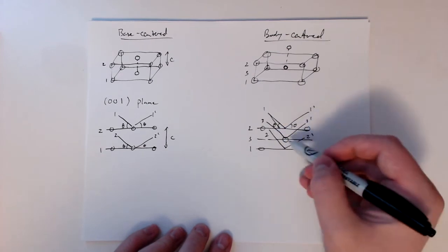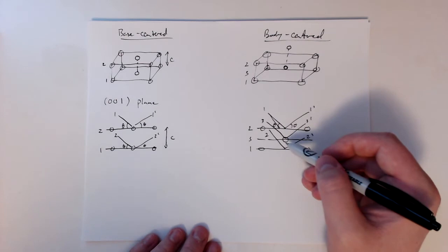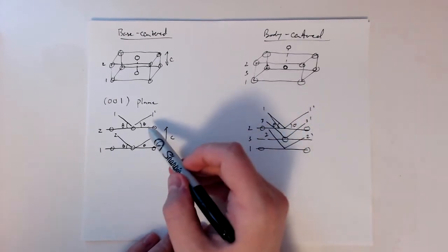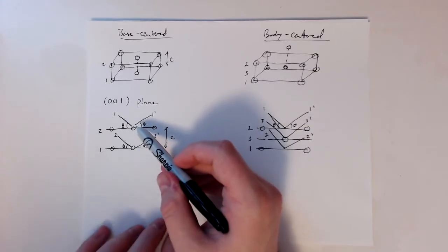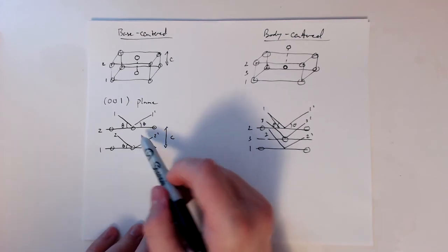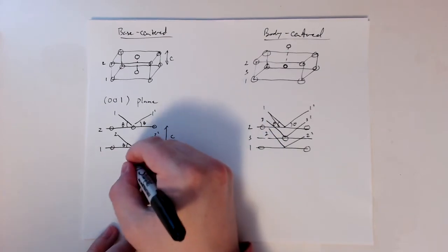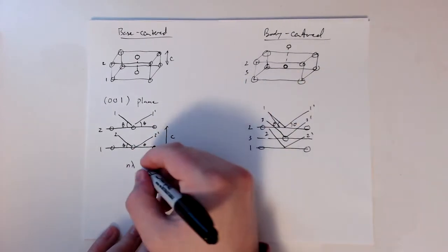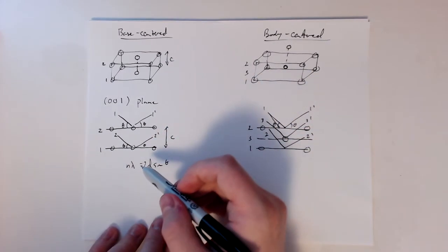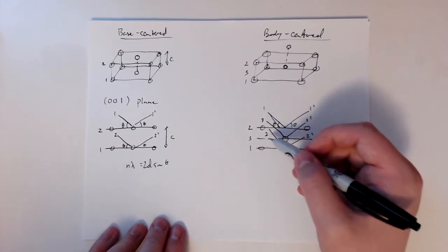So the fact that I have the middle atom halfway between these is important, because if we think about the issues here, if this causes constructive interference, the extra distance that the second beam travels is an integer value of lambda, right? That was 2d sine theta. So that satisfied the Bragg condition. So that also would mean that the same is true for beam 1 and 2 over here.